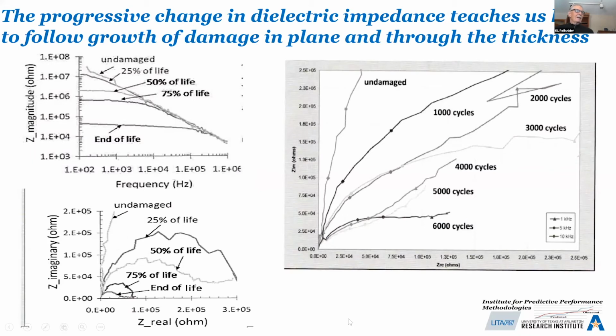Let's look at the left-hand top first. This is the dielectric impedance now, the inverse of the permittivity. And this is frequency of oscillation down at the bottom. You can see it goes from very slow, a few cycles a second, up to about 1 times 10 to the 6 cycles per second. Rapid on the right, slow cycling of the voltage on the left. And he gets a really big difference in the impedance depending upon what he does.